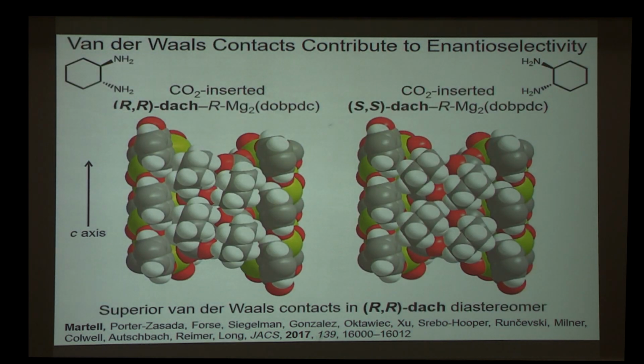This is now a space-filling model of the same structure. As a reminder, the diamine contains a cyclohexane ring. Each of these objects here is a cyclohexane. And what I found is that this diastereomer had more favorable van der Waals interactions. It may be hard to see the subtle difference between these two, but these arrows should make it more clear. I found in this case, there was more favorable van der Waals contacts between cyclohexanes and also for the cyclohexane interacting with the wall of the MOF pore.